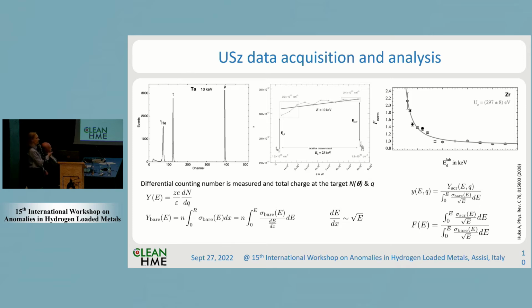So for the bare nuclei case, we have the kind of graphs that you see over here. We have few counts over here, few counts over here, and few counts over here. And we manage to say what kind of differences there are between the different energies studied, okay? Then these so-called enhancement factors are plotted in a plot like this, and then we can use the function to check what is the screening energy.